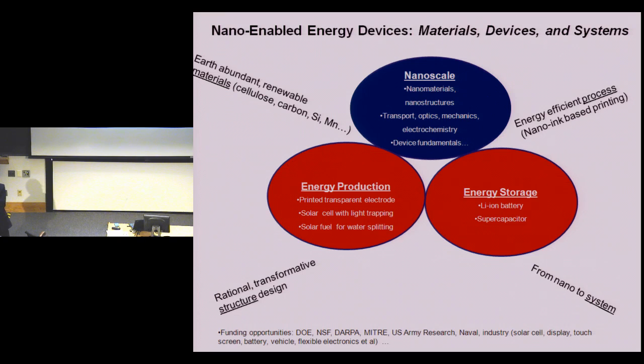Just following up on that, the softness of the silicon depends upon the thickness of the silicon on the nanostructure, and also the stress concentration depends on that. Go to the full concentration of lithium, you have thinner silicon layers, and maybe just a denser network. Exactly. I think as we decrease the thickness of silicon, the stress building up should be smaller. And that will also allow us to do the full capacity charge and discharge. But in the meanwhile, we need to remember that we need enough silicon material to get enough charge stored inside the electrode.